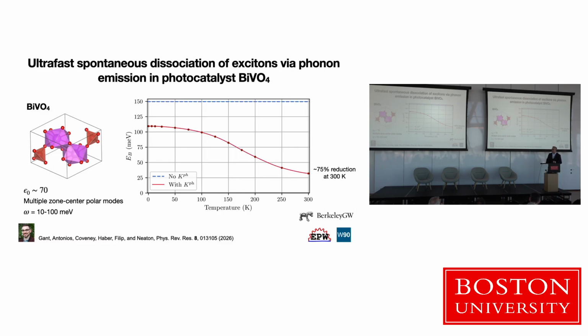It has to be stable under water oxidation conditions, and it has to be stable under bias, and Pourbaix diagrams, et cetera, won't go into it. But essentially, there are some criteria that it actually satisfies. So it's interesting, but it's an oxide, so an unconventional semiconductor. But the state-of-the-art theory predicts that it has an exciton binding energy of about 100 meV, which is a few factors above kT at room temperature.